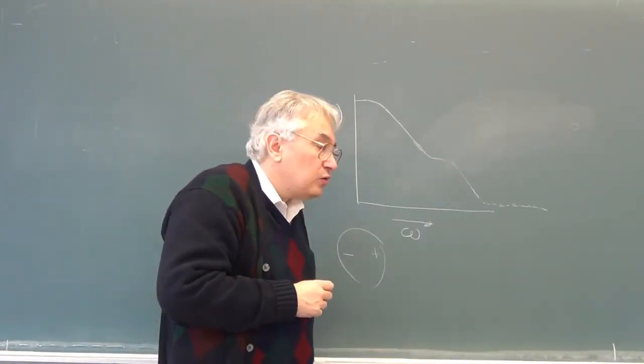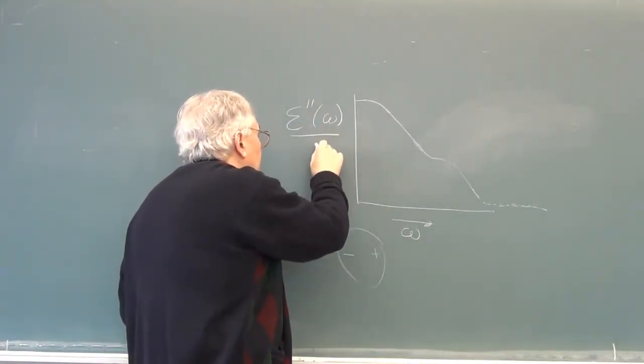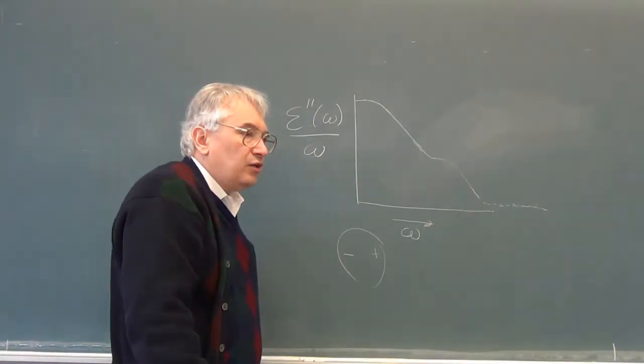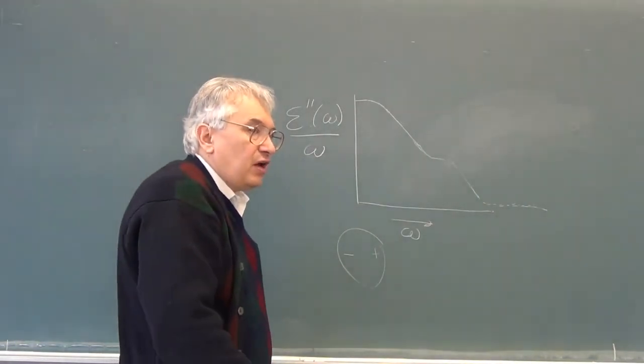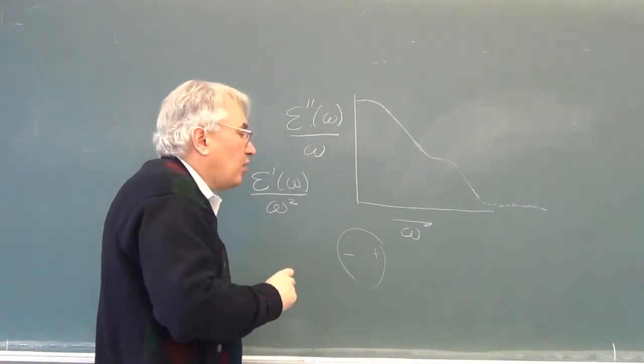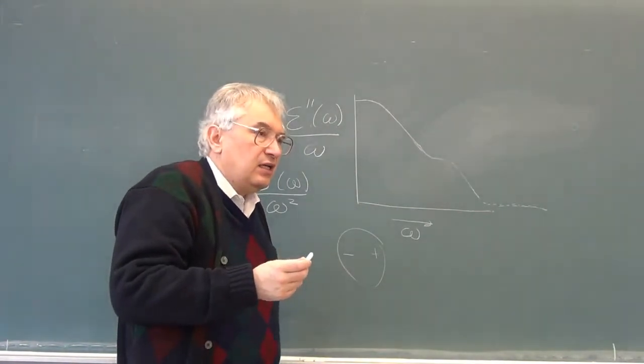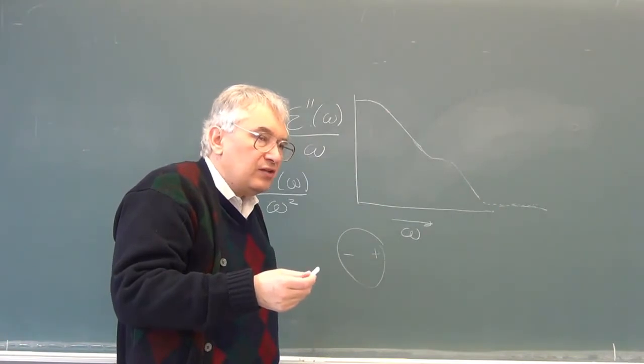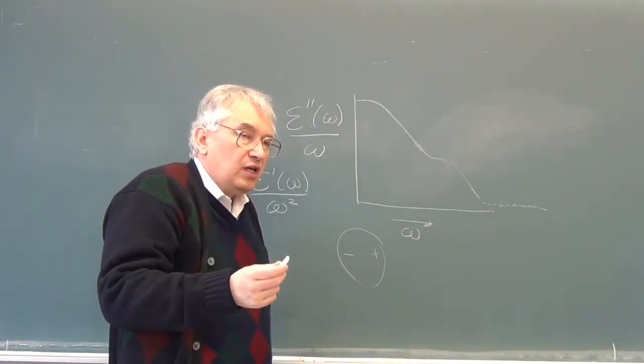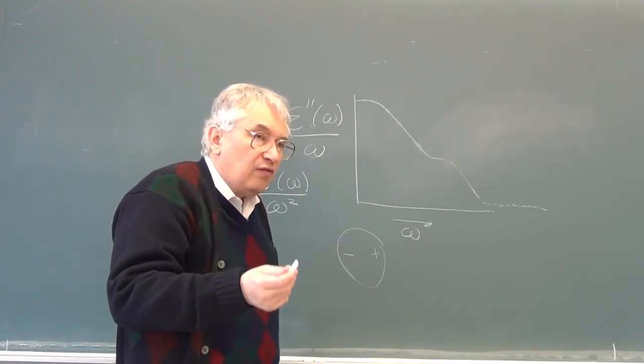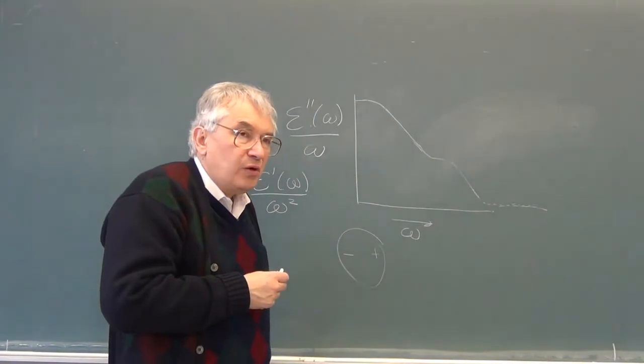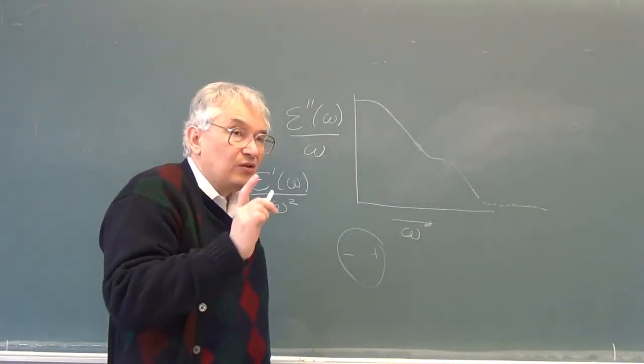If you want to line these dipoles up, the electric field has to point in the same way long enough for the dipoles to get turned around and point in the needed direction. If before the dipole can move significantly you flip the direction of the electric field, the dipole now tries to start moving back the other way, nothing much happens, and it does not contribute to the dielectric constant of the material. This is the loss function — that's frequency — and as you run up the frequency, things fade.